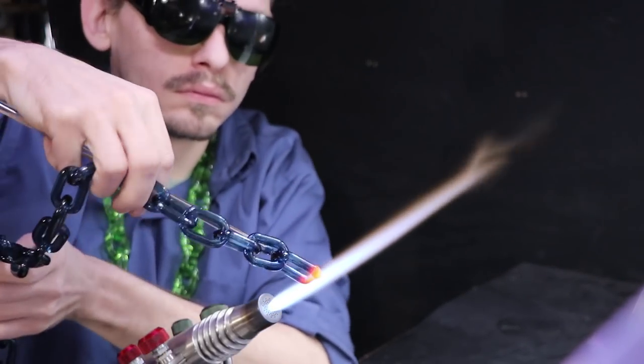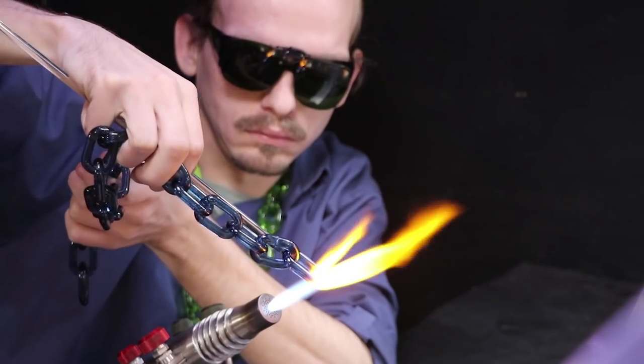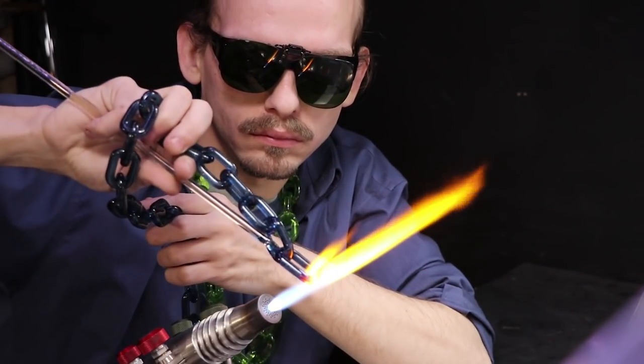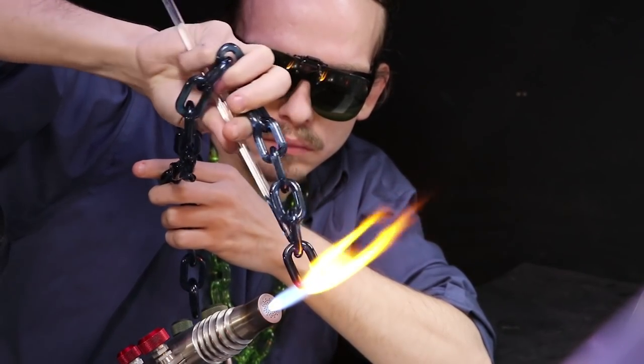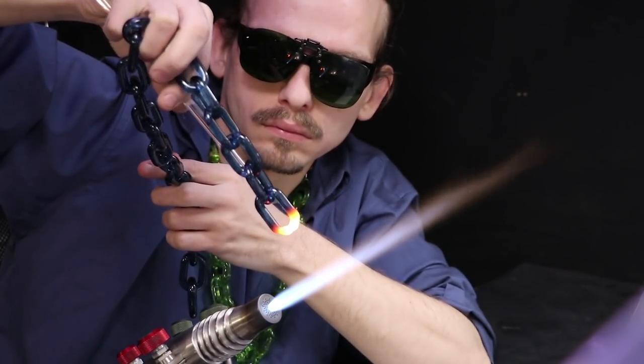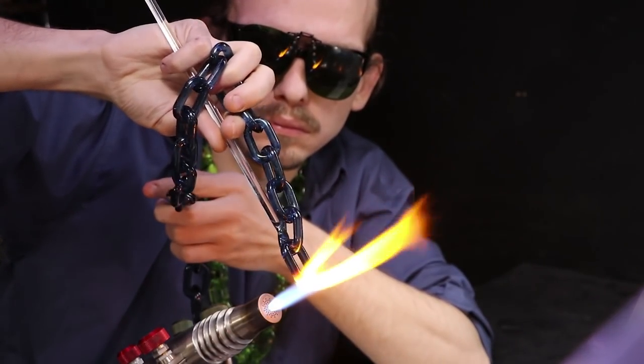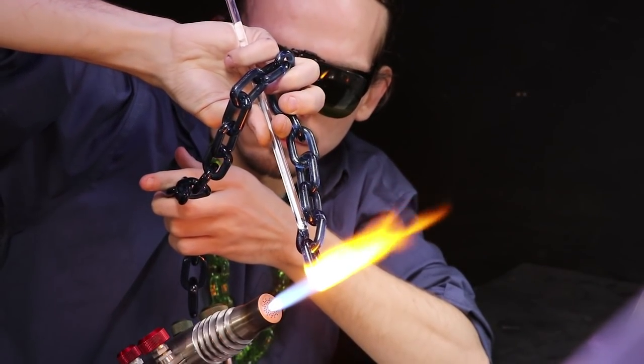And so with that, I'll go ahead and hold it at a slightly downward angle and keep rotating. This will melt the glass, condense it, bring it together, and then gravity will help pull it down into that nice loop shape. And so if I were to tilt it more towards the floor, like straight down, it'll start to pull the loop out more, kind of thinning it out. But if I tilt it more level or more up, then it will start to condense back and thickening the loop. So finding that correct angle and with good heat control, you can form up that loop without using really any